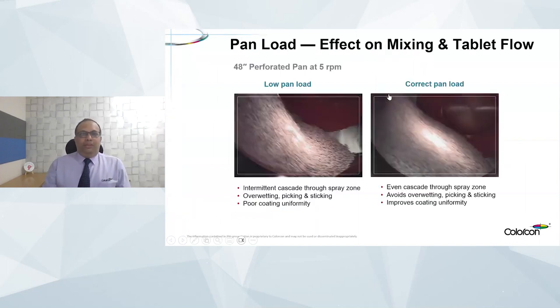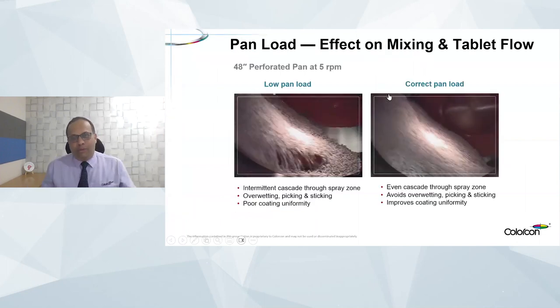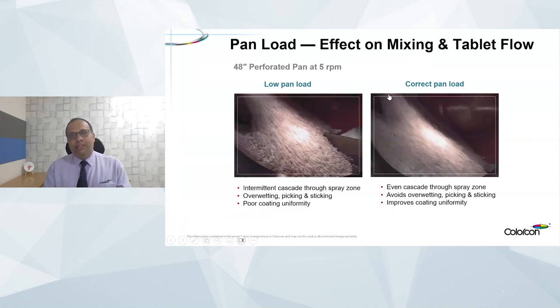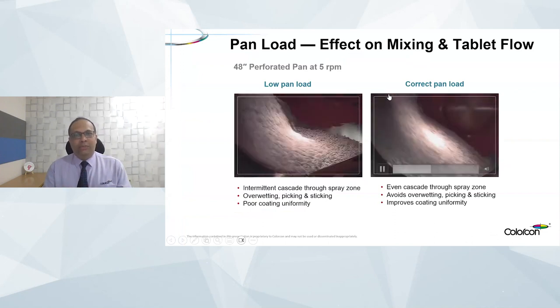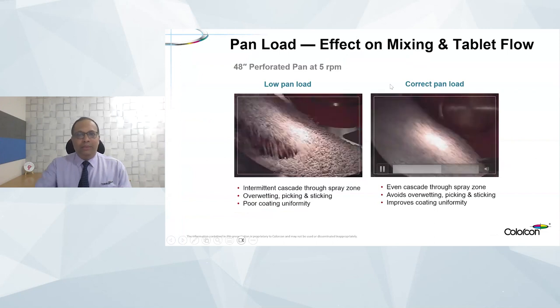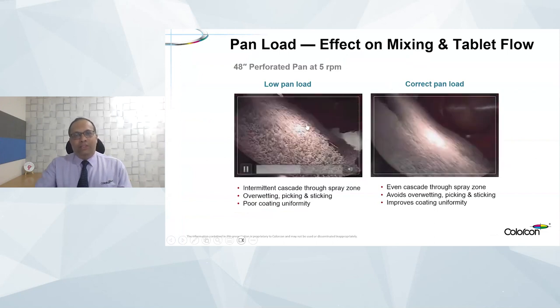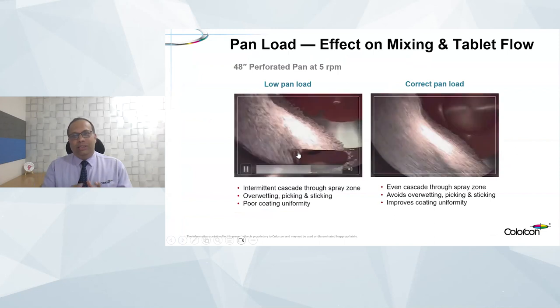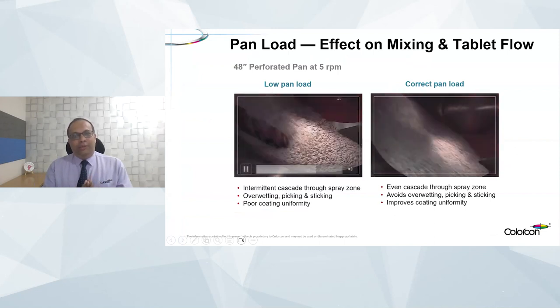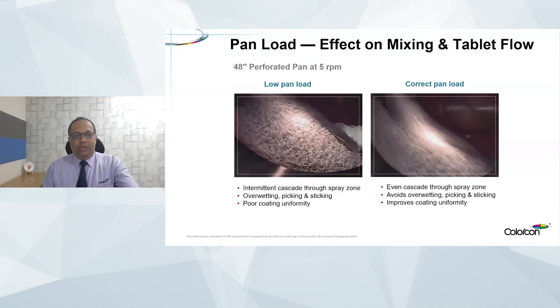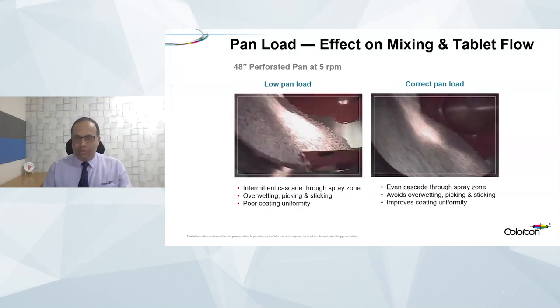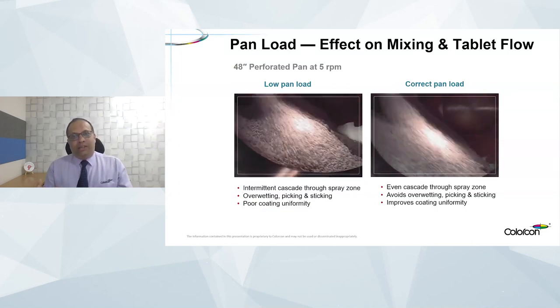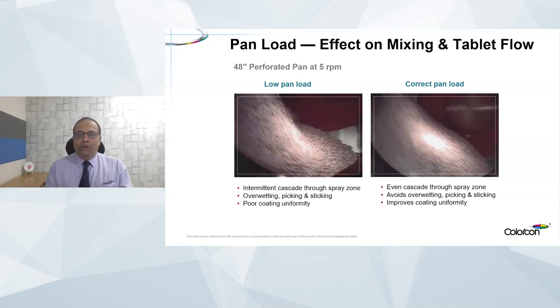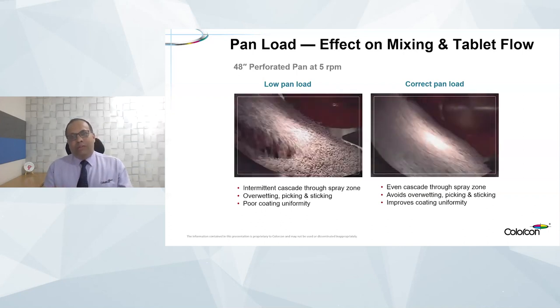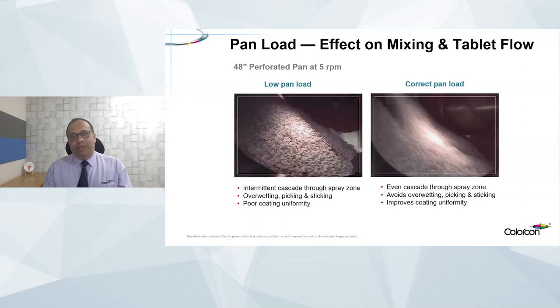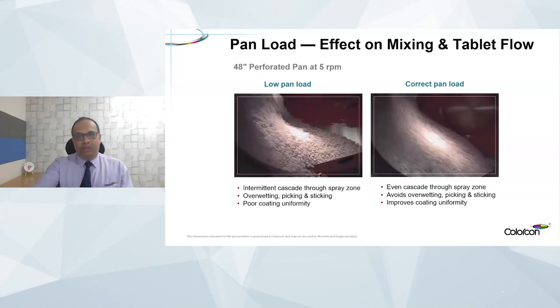So you can see, from the perspective of coating uniformity, how well the tablets mix inside the coating pan is important. You could see a 48-inch perforated coating pan running at 5 RPM. When the load is insufficient, you would see the tablet bed stopping inside the spray zone, so there is intermittent cascade. There could be overwetting or poor uniformity. Whereas if the pan load is correct, at the same RPM, you could see a much more uniform cascading movement of the tablets, which would definitely improve the overall tablet coating performance.